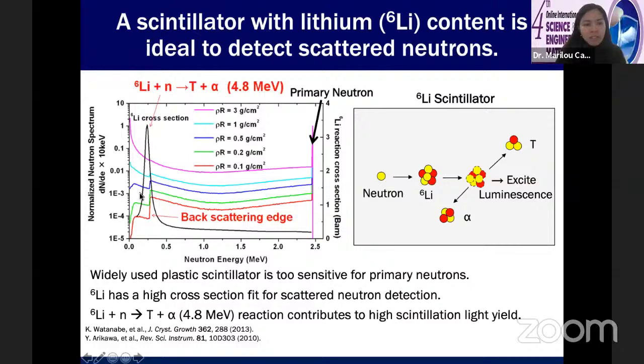But if we look at this black curve here, it's the interaction cross-section of lithium-6 with the neutrons. We can see that lithium-6 has a high cross-section of interaction with the scattered neutrons. So if we wanted to detect the scattered neutrons, we should use a scintillator with a high lithium-6 content. Essentially, the neutrons will interact with the lithium-6, and that interaction will generate triton and alpha rays. The alpha rays will then excite the scintillator, and the scintillator will emit luminescence, which is what we can detect and relate back to the scattered neutrons that interacted with lithium-6.